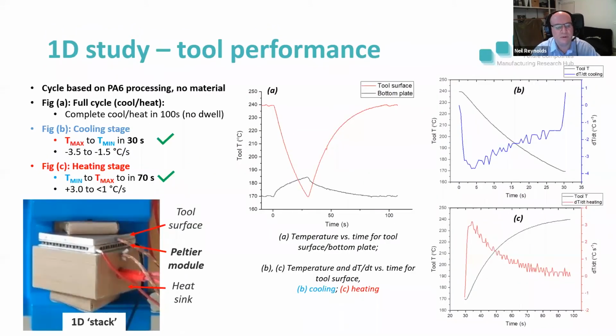The first part of the work we completed is a 1D study on a single module. You can see the stack in the bottom left picture. You've got the tool surface and the Peltier module in the middle, and then the heatsink behind it. The data shown here is an example cycle for a polyamide 6 process with no material, just the tool surface. So we're going from 240 degrees down to 170 and then back up.